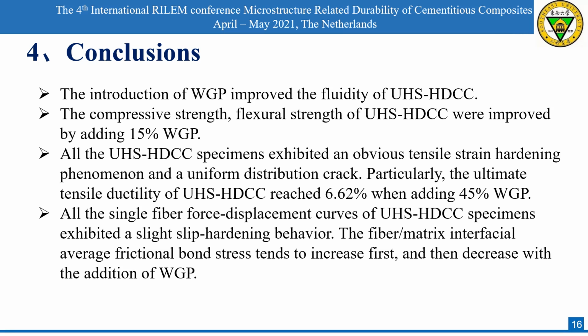All the single fiber force-displacement curves of UHS-HDCC specimens exhibited a slight slip-hardening behavior. The fiber and matrix interfacial average frictional bond stress tends to increase first and then decrease with the addition of WGP.